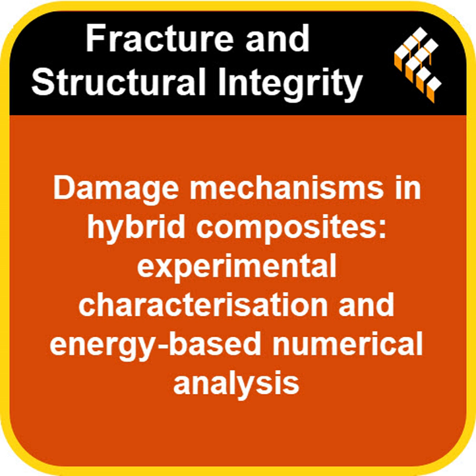Right. The friction between layers also behaves differently depending on the glass fiber's location, potentially indicating how the layers are interacting or separating. In the hybrid materials, the outer carbon layers tend to absorb the most energy through internal damage. Having more layers packed in the middle helps to limit how that damage spreads through the thickness. And more glass layers generally mean less internal damage accumulating before you reach that peak force. Okay. And finally, they saw that the specific way you layer the carbon and glass fibers really affects how the layers start to separate, those delamination patterns. Ultimately, the study shows how we can better design these hybrid composites to withstand bending in specific ways, and importantly, to control how damage progresses within the material.